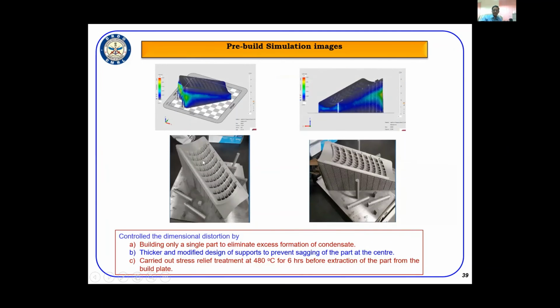Then again we went ahead with the dimensional analysis of the component. You can see that the whole component is within the required dimensional requirements, whereas all the other deviations have come into the support structures. To eliminate excess formation of condensate, we built only one single part. Earlier we had taken 2 parts in the same deposition. In the next stage we took only 1 part, and a thicker and modified design of supports was made to prevent sagging of the part at the center. This way we could overcome that problem, and we carried out stress relief treatment before extraction. So the component is now meeting the dimensional requirements in full.